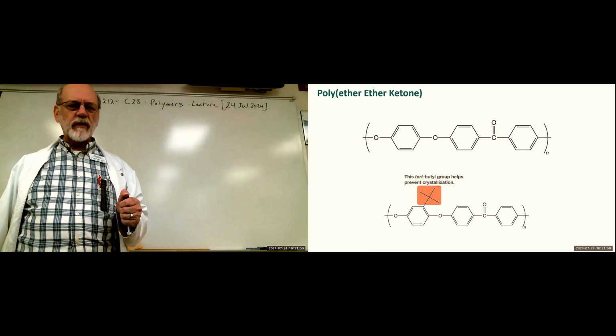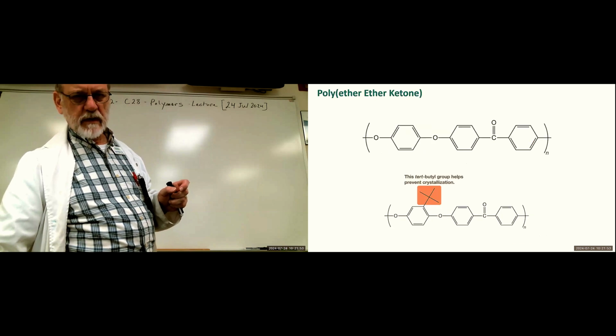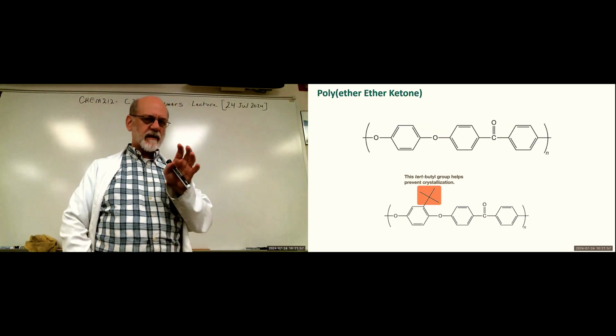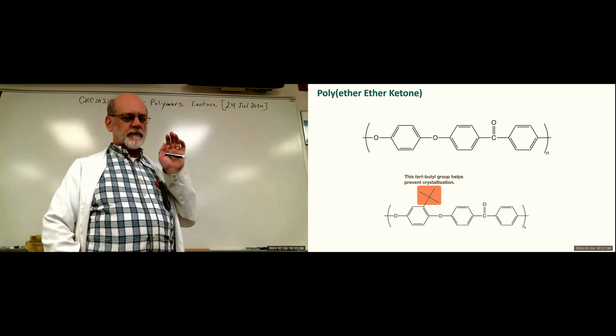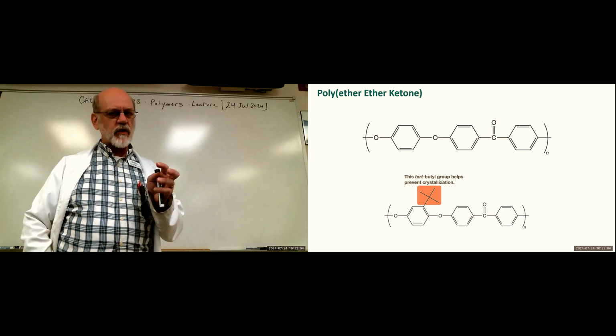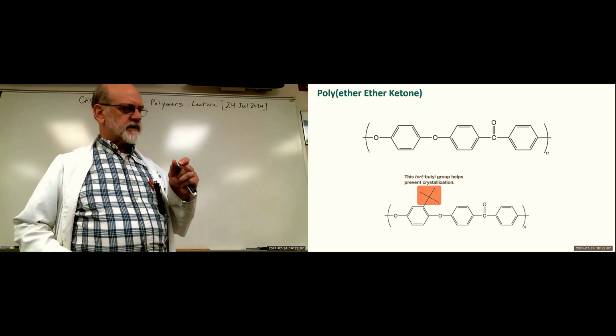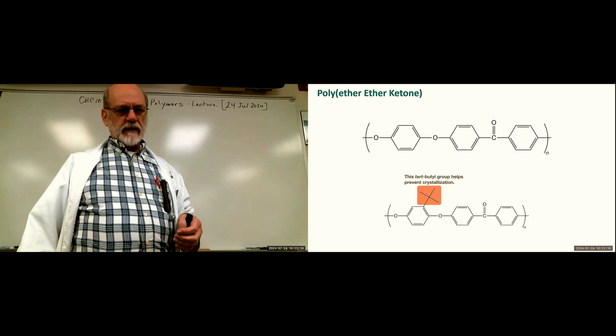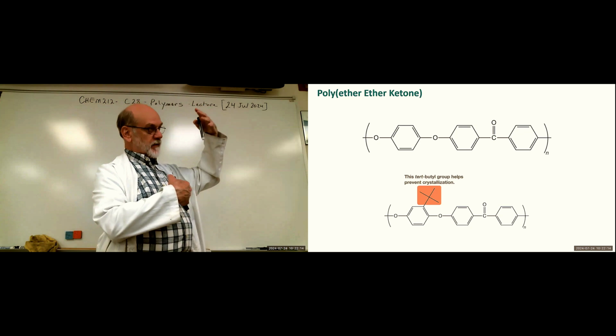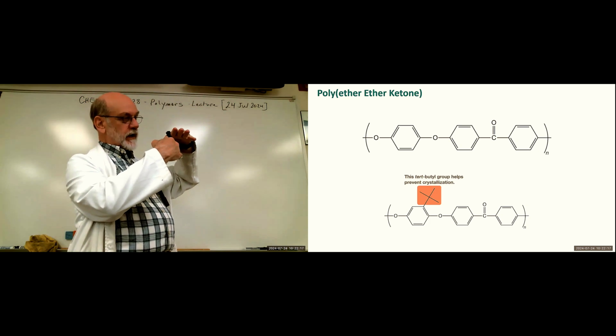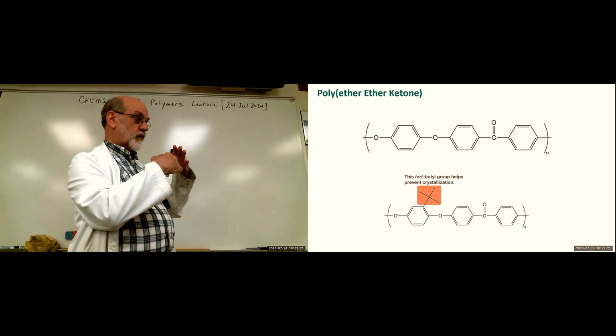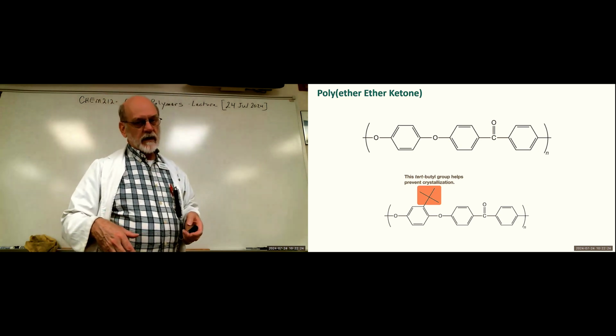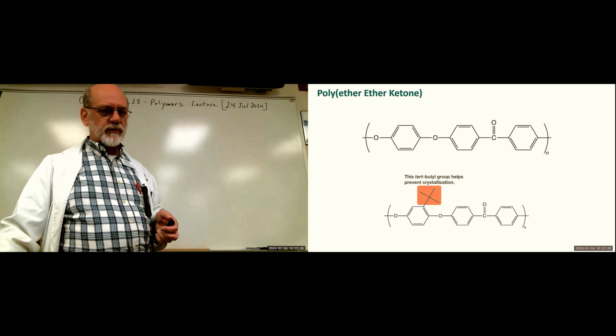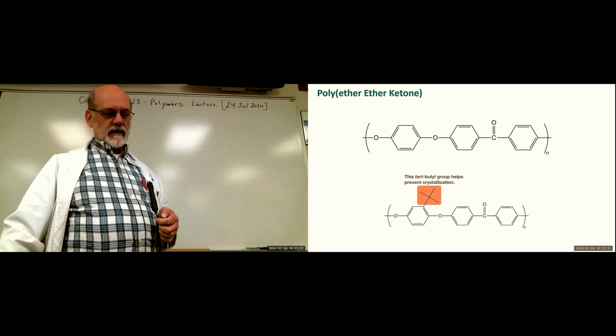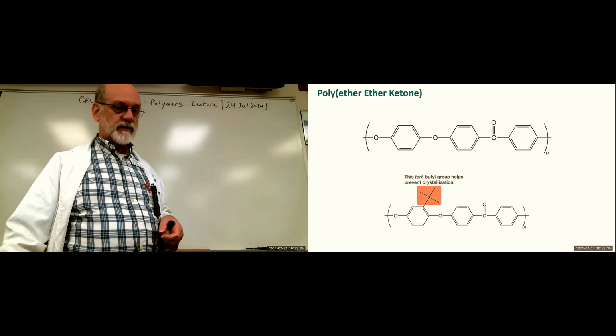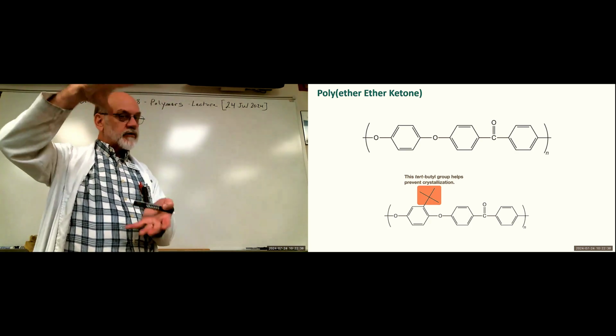The problem with trying to make PEEK from the monomers is that as it grows, it tends to crystallize, because it has that rigid backbone, those phenyl groups. The neighboring polymers will associate with one another. They won't form covalent bonds, but they will form the intermolecular forces that cause it to crystallize. So the way around that is to add tertiary butyl groups to the monomers. They don't interfere with the polymerization, but they keep it from crystallizing because that bulky group keeps the molecules from getting close to one another.